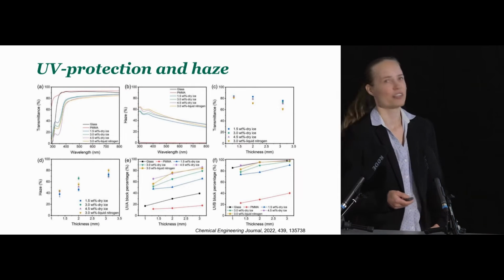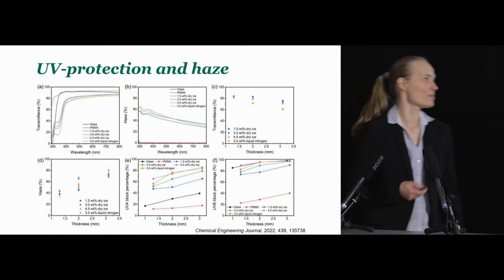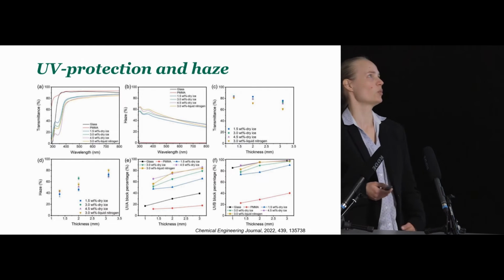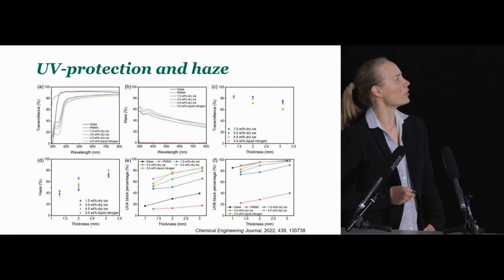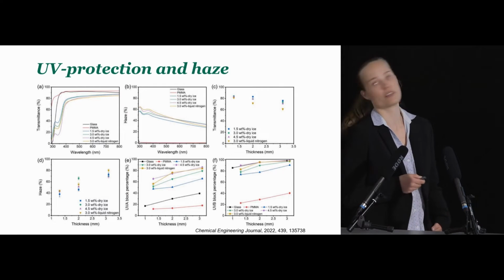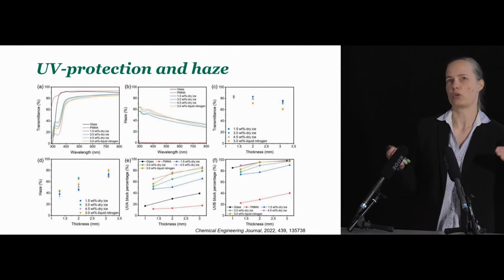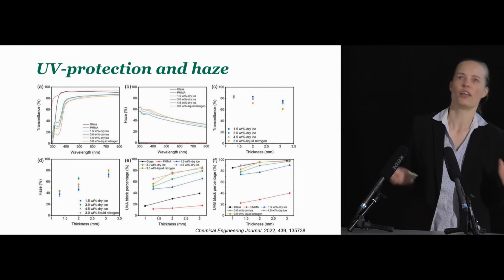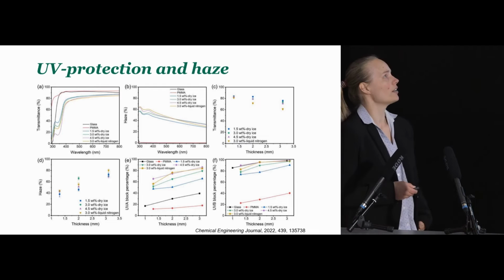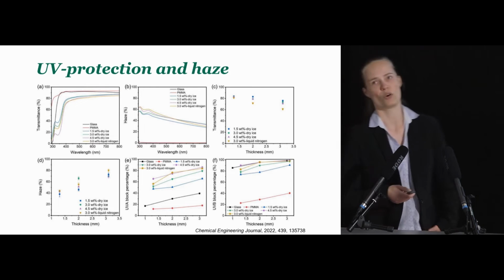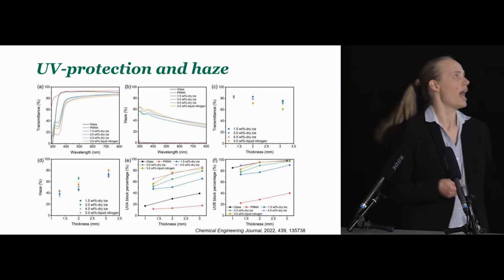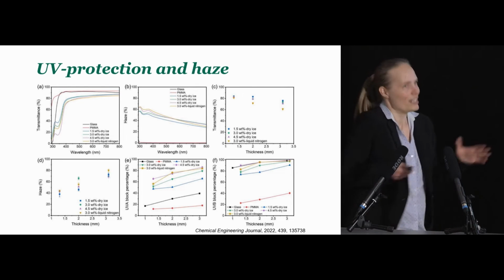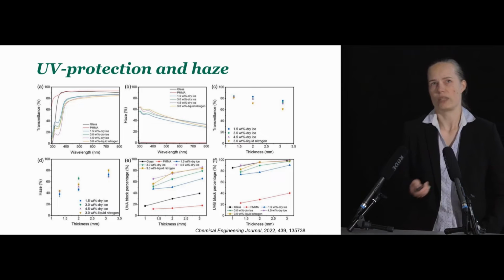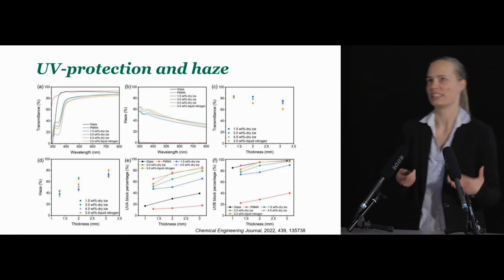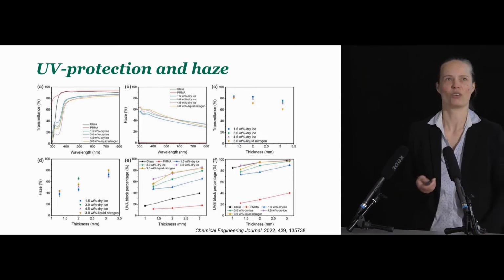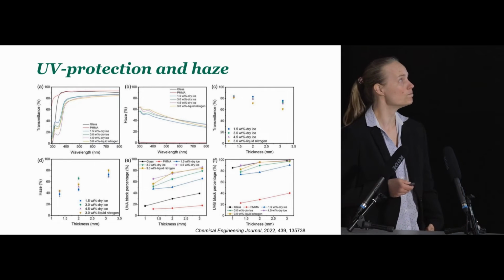So here are the optical characterizations of these composites. I'm not going to walk you through all of this, but I want to highlight a few things. First of all, this haze component is the percentage of the transmittance that goes towards diffusive transmittance, which helps us collect more light. And in these composite films we had over 80% of total transmittance and approximately 50% of diffusive transmittance. The research is still ongoing, but we believe that this might be quite a good ratio for this type of translucent films.